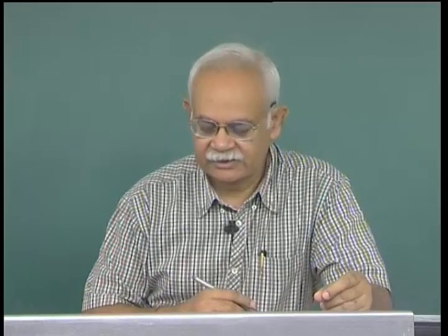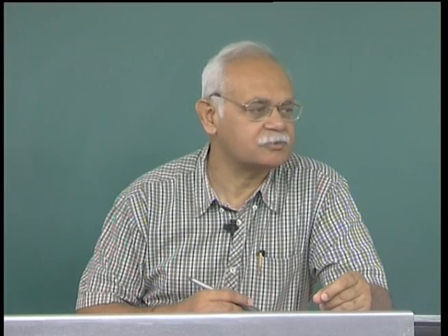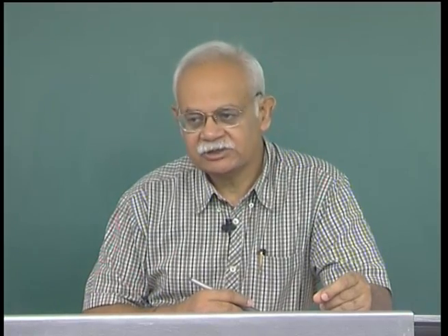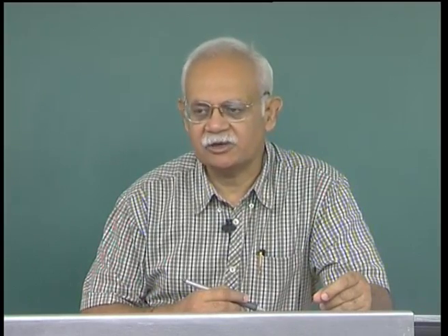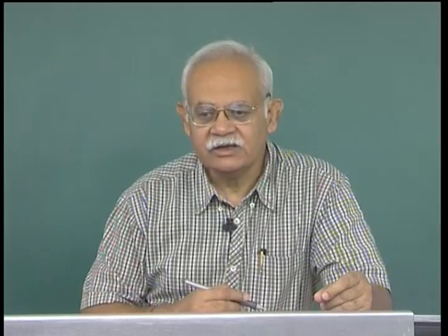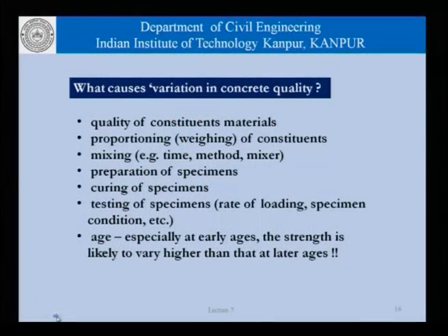The testing of the specimen, that is the rate of loading, the specimen condition. The specimen is tested after it is taken out from water. Whether the specimen is tested while it is wet, or is it allowed to dry out, and so on. At what rate is the load applied to the specimen? Whether we are using load control or displacement control machines, what is the stiffness of the machine that you are using to determine the strength of concrete? All these parameters will cause a small perturbation in the strength that we determine from one specimen to another. Age, especially at early ages, the strength of concrete is likely to vary much more than at later ages.